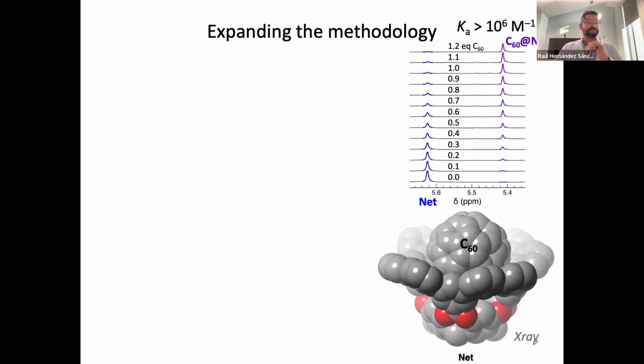Anyhow, the point is that there's really strong binding of fullerenes by these particular nets. So here you have the free net, zero equivalents of C60 added. This is the acetal resonance. So it's one of the resonances pointing right here towards the C60 molecule. And as you can see, as you add equivalents of C60, you start seeing the coexistence of the host-guest complex and the free host, meaning that there's essentially in this solvent no equilibrium. The moment you add C60, the equilibrium is pushed all the way to the right, you form the host-guest complex and you have free host. There's no back and forth. That's why you don't see the monotonic change that usually you observe in a titration experiment.